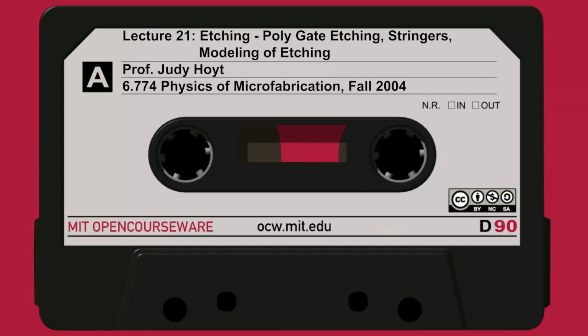Tungsten can be etched in SF6 or chlorine. So you notice a lot of the metals, these are all metals, are attacked by chlorine, which isn't too unusual if you know a common wet metal etchant is hydrogen chloride, HCl. Again, for etching titanium or titanium nitride, very common etchants are chlorine or mixtures of chlorine with hydrocarbons.